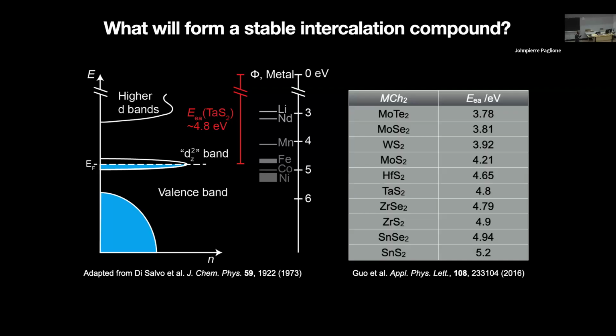Now, again, this model is only considering that charge transfer, but you're making a covalent bond between the transition metal and the host. For example, Leslie here has shown that palladium can do interesting reactions with tellurides. And you'd say, well, molybdenum telluride or tungsten telluride have very small electron affinities, but if you think of it like hard, soft, acid-base chemistry, that palladium is a soft thing, and tellurium is soft, then maybe the covalent interaction can promote some interesting chemistry. So this is purely thinking electrostatically about it. But in general, for these transition metals, we're stuck to the group 4 and group 5 chalcogenides so far. Okay.